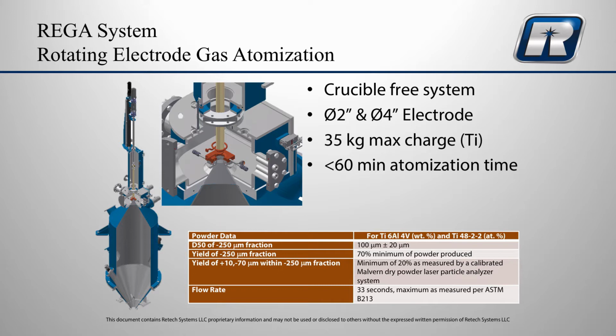We are looking at the 2-inch or 50 millimeter and the 4-inch or 100 millimeter diameter configurations to melt charges up to 35 kilogram maximum. And the melt and atomization time will also be less than 60 minutes. This process is typically known to produce finer powder, and our data also confirms that it can produce a finer powder. So our D50 of the minus 250 fraction, we certainly are going to guarantee 100 microns. And the powder yield is a minimum of that size fraction, a minimum of 70%.